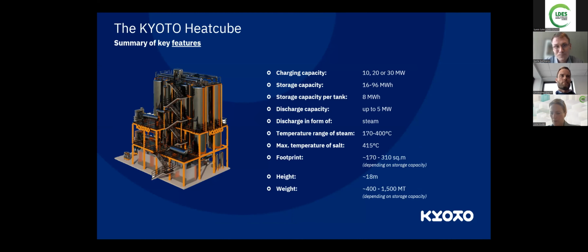Here is a little bit about the key features of our system. As said before, charging capacity can be scaled to the need of the customer, 10, 20, or 30 megawatt electrical. That then goes into thermal. The storage capacity depends on how many tanks you put together, so between 16 and 96 megawatt hours. Discharge capacity is up to 5 megawatt. With discharge in the form of steam, it can be both superheated and saturated steam, and the temperature range of our steam is between 170 to 400 degrees. Our salt temperature is 415 degrees, and the footprint is around 250 square meters, up to 310. The height is approximately 18 meters, and the weight is between 400 to 1,500 metric tons.